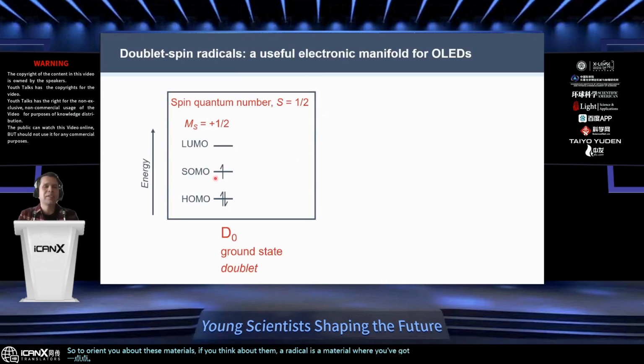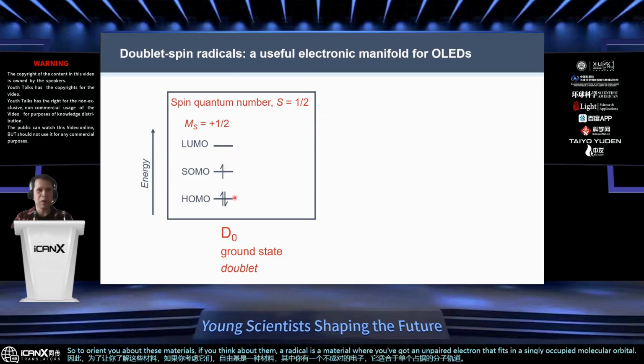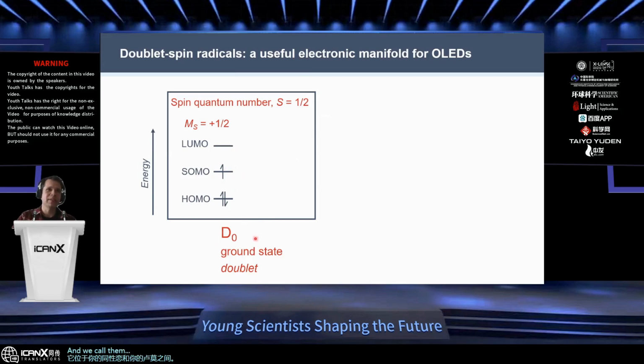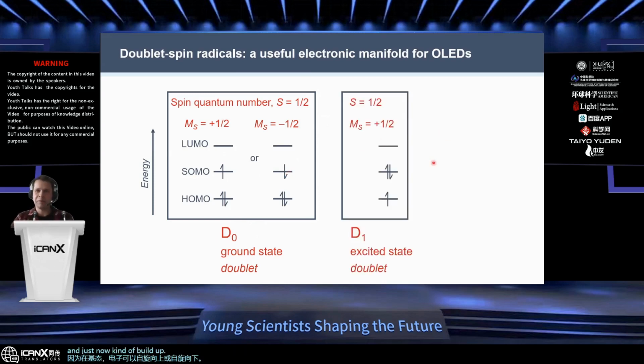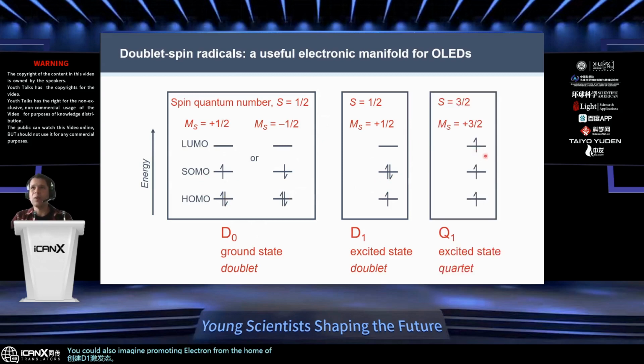So to orient you about these materials, a radical is a material where you've got an unpaired electron that sits in a singly occupied molecular orbital, and it sits between your HOMO and your LUMO. Now, we call them doublet materials because in the ground state, the electron can be spin up or spin down. And to build up the spin playground of these materials, if you want to think about how you can excite it, you can imagine a transition from a HOMO to the SOMO to create the D1 excited state. You could also imagine promoting an electron from the HOMO to the LUMO. And if the electrons are aligned in this configuration, you form quartet states.